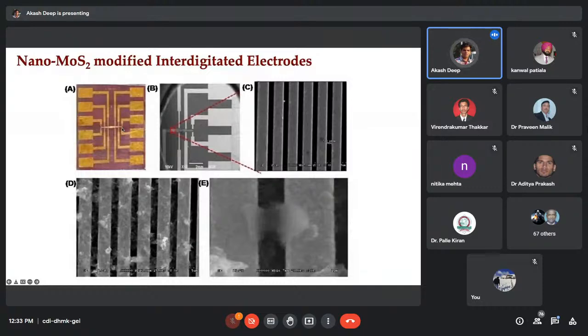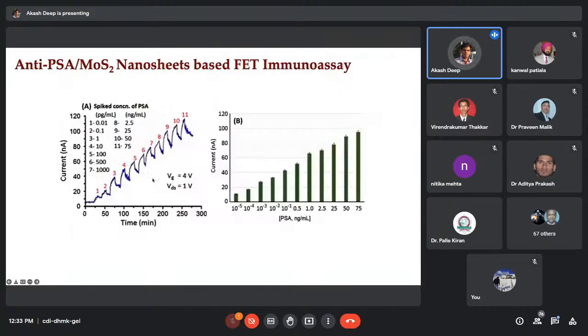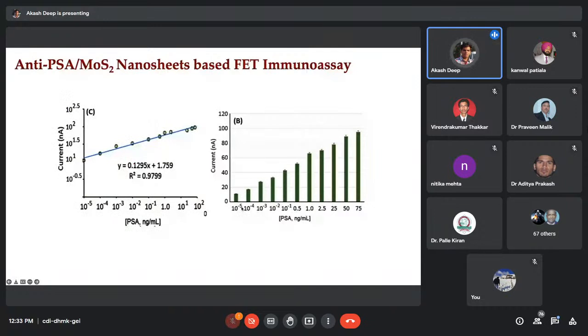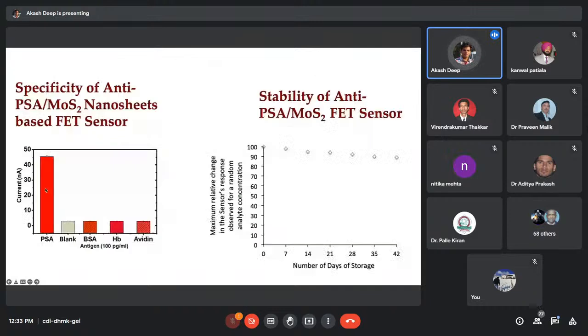We don't have to reuse different electrodes for different concentrations. So a single chip can be used for multiple analyses. In this case also, we achieved a very good calibration curve. You can see that the PSA could be detected from this low concentration, 10 to the power minus 5 nanogram per ml to 75 nanogram per ml. This is the specificity test, so we confirm that this is only giving response to the desired antigen.